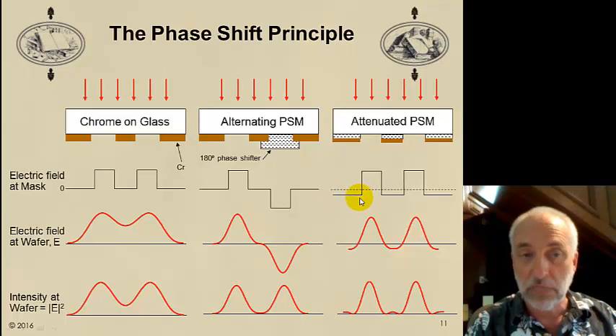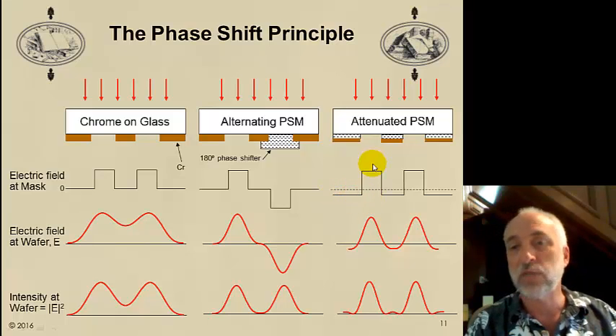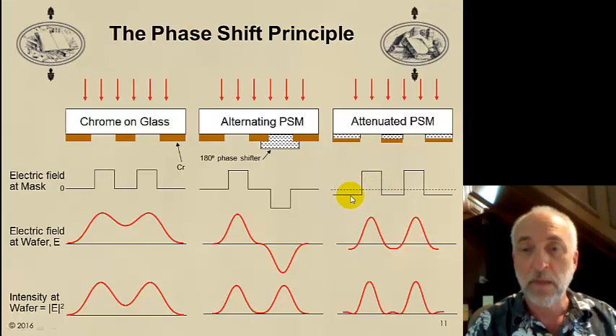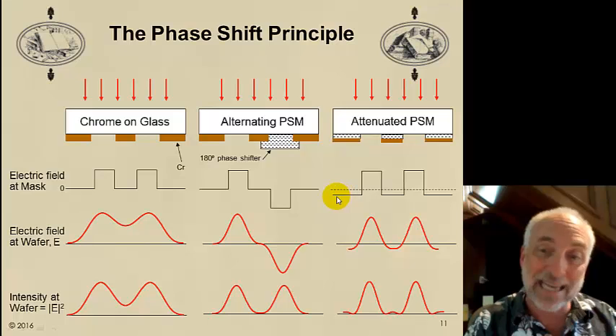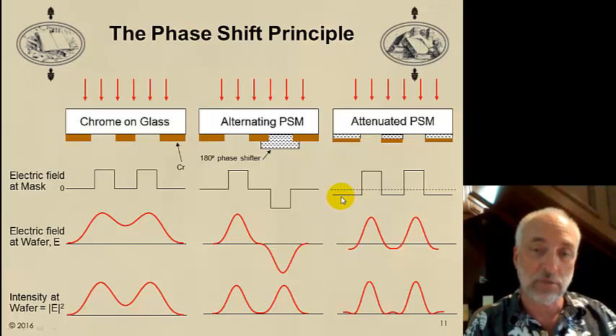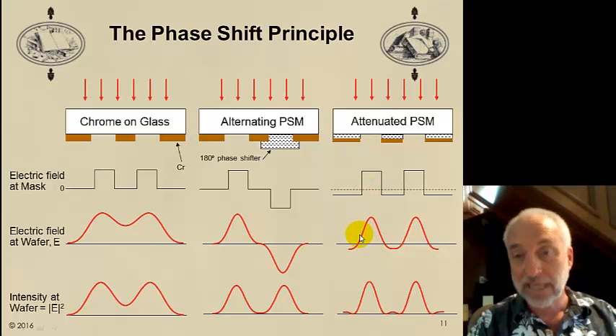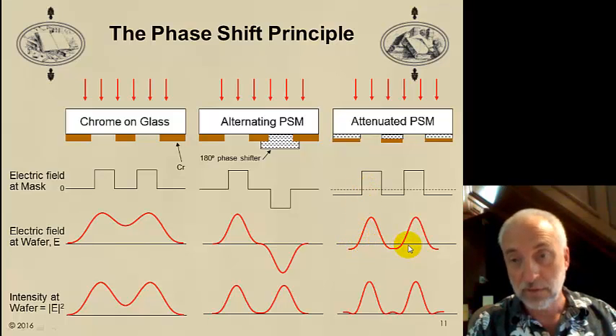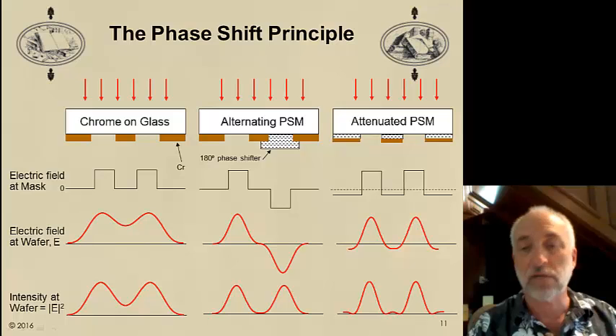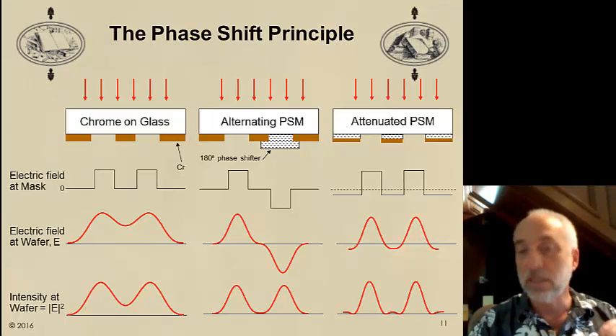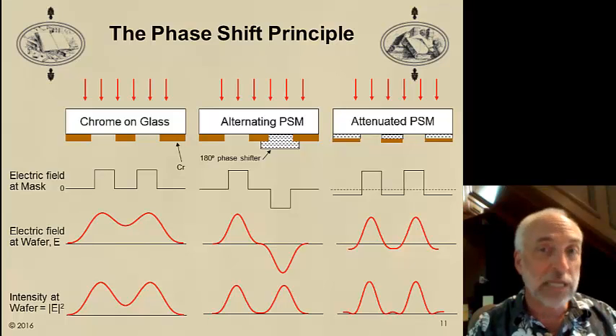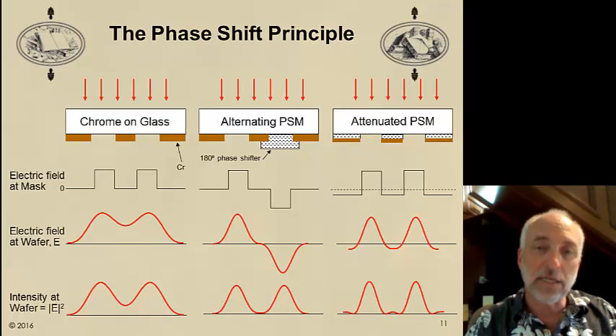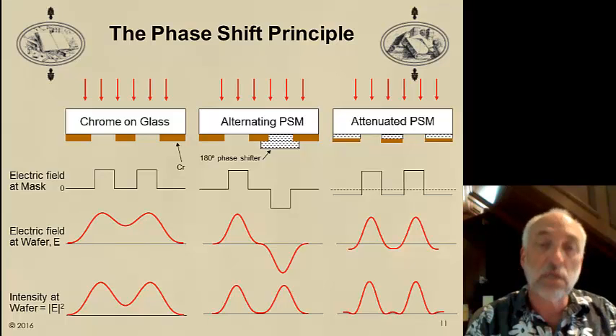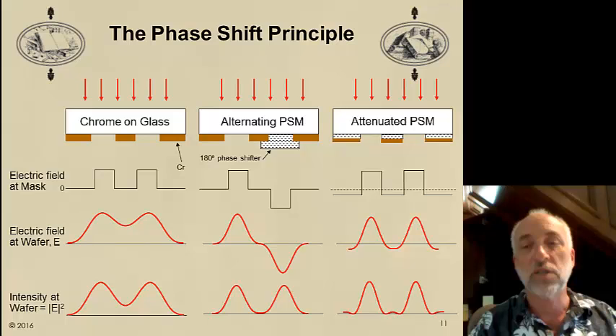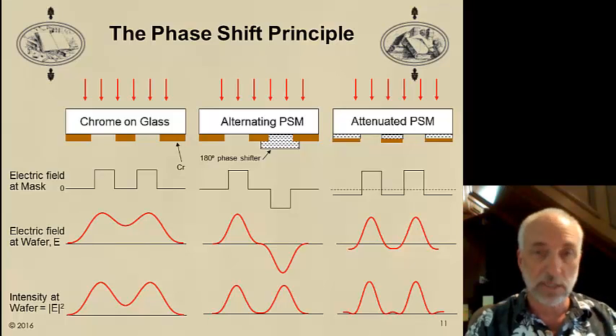So while this is an electric field that's, say, maybe 25% transmitting compared to over here, it is 180 degrees out of phase, so it's a negative 0.25 electric field. That means the electric field passes through zero to go from plus to minus. And when I square the magnitude of the electric field to get the intensity, I have light going to zero. You see what the phase shift does is zero light and 180 degree light, light that's out of phase with each other, combines to make darkness. And we use phase shifting masks to control the darkness and get better quality images.